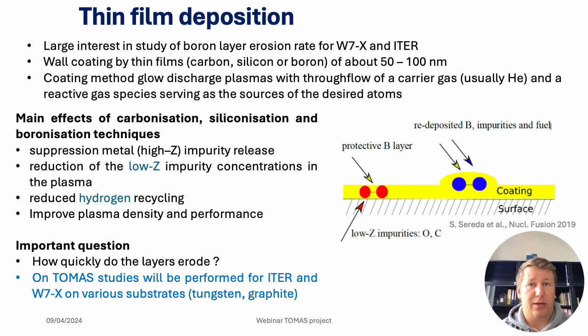The most common thin film deposition technique is boronization. It involves coating walls with a layer of boron. Currently, this type of wall conditioning cannot be done directly on TOMAS due to some safety restrictions. However, we can contribute to studies of boron layer erosion using our machine. The problem is that the deposited boron layer is eroded during the consequent plasma experiments. By exposing the boron-coated material samples to the TOMAS wall conditioning plasma, we can estimate the erosion rates of boron layers and extrapolate them to large fusion device operation scenarios.